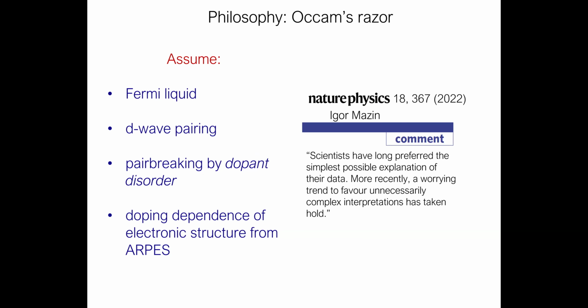So David Brun, Vivek Mishra, Steve Dodge, and I tried to take an approach where we're going to assume the simplest possible thing. We're going to assume that there is a Fermi liquid, that we have D-wave pairing, that we have pair breaking by dopant disorder, and that we take the doping dependence from the observed electronic structure in ARPES experiments, changes of the Fermi surface. Put all that in and see if we can explain these experiments. And this is sort of in contrast to this trend that Igor Mazin commented on in this inverse Occam's razor paper, which I recommend to you if you haven't read it.